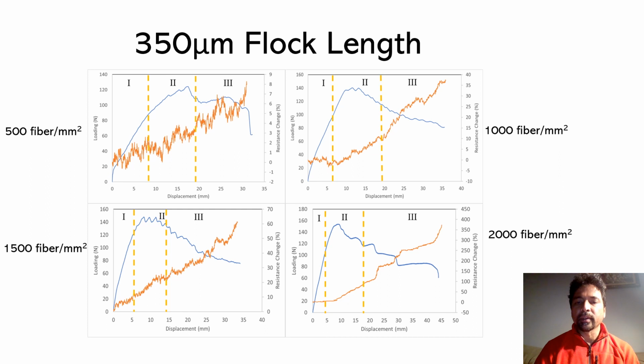However, if you see 2000 fibers per millimeter square, it is actually much higher, which is 400%, because as the crack is propagating, you are breaking the network perfectly between the 2 interfaces. That's why you see a very high resistance change. Moreover, the initial resistance of the systems decreases as the flock density increases. Hence, you see the maximum resistance at which they break is also increasing.